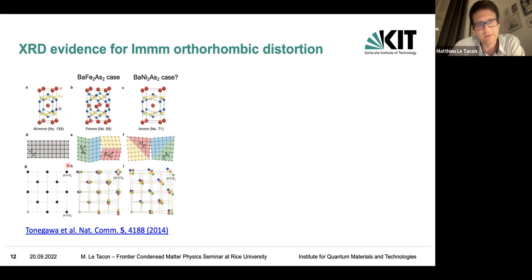So you go from the tetragonal phase, and then they discuss whether you would have a distortion to the FMMM space group or the IMMM space group, which are two possible orthorhombic distortions. The first one, the FMMM, is the one that you see in the iron-based case, whereas the IMMM, from a group symmetry point of view, would be the one we're dealing with in the nickel case. So in the phosphorus-doped compound, if you want to see this in diffraction, you see this twinning effect. From the twinning, you see a splitting of the different Bragg peaks, and the splitting increases as you increase the order of the reflection.